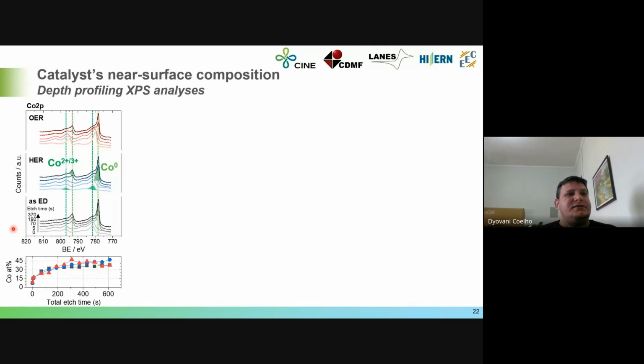We can see that the surface is composed of hydroxides, more part of metal oxide. So here we have a lot of cobalt oxide. But underneath the surface, we have metallic cobalt. This peak and this peak are characteristic of metallic cobalt, and these peaks and this one are characteristic of cobalt oxide. And this happens after hydrogen evolution reaction too. We can see some cobalt oxide, even underneath the surface, but deeper, we can see the metallic form.